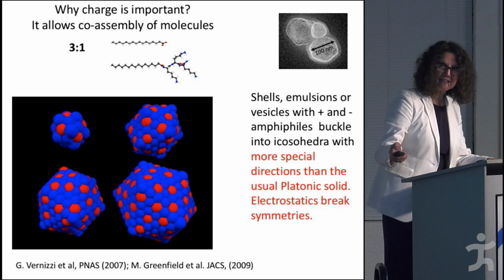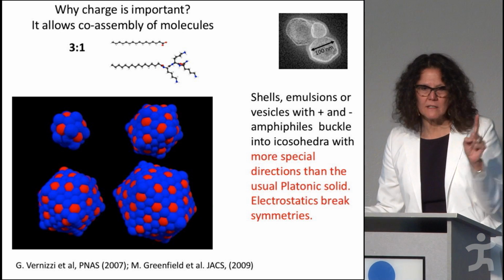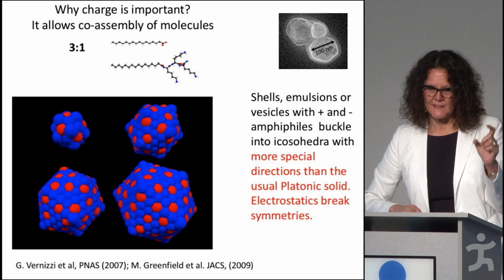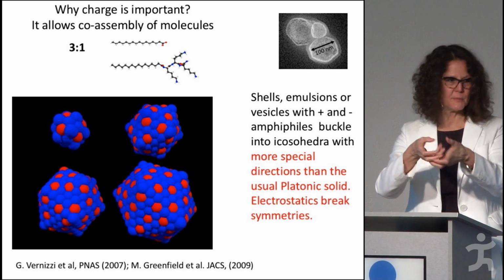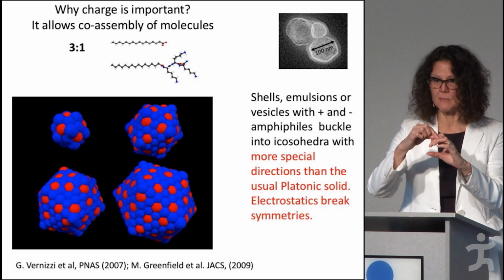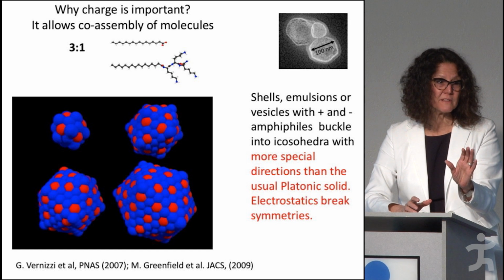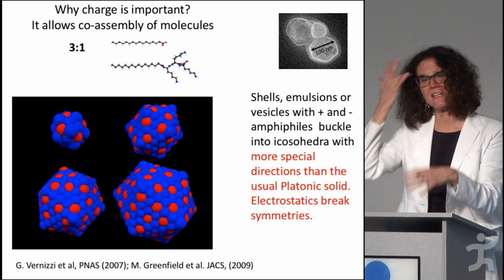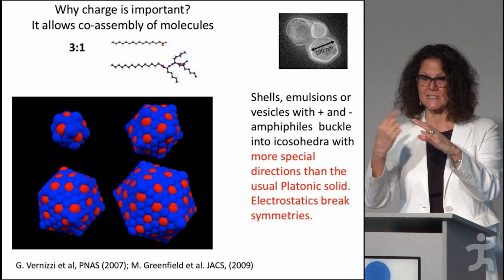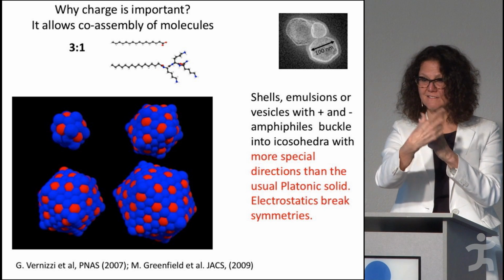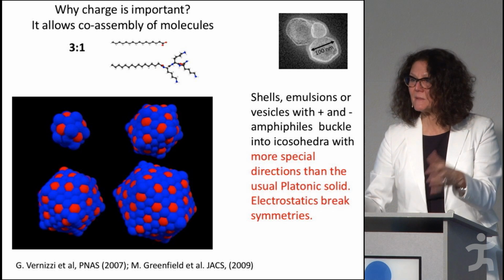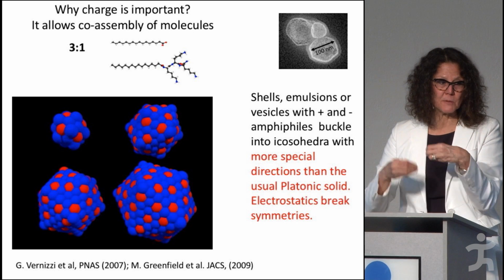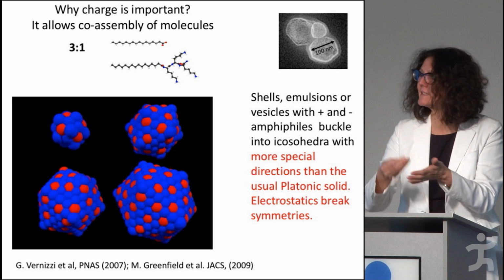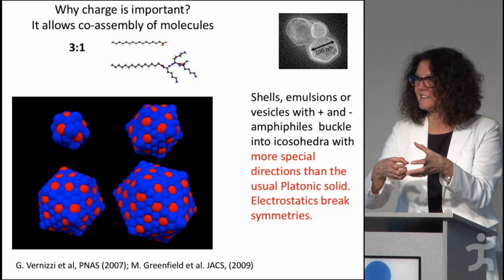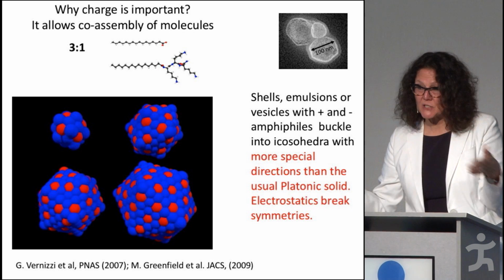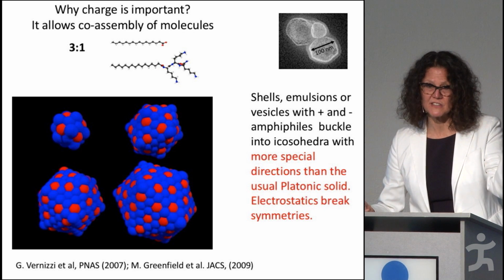And the resulting object, this was an icosahedron, but this icosahedron does not have icosahedral symmetry. And so let me explain this way. If you have a cube, it has a cube symmetry. But now if you are playing dice and you put labels 1, 2, 3, 4, 5, 6, now it doesn't have any more cube symmetry. You broke the symmetry because you have the labels. When these icosahedra have charges, what we find is that they break rotational symmetry, and each triangle in the icosahedra is not equivalent. They change the distribution. So it was very interesting because it means that this electrostatic interaction breaks symmetry spontaneously. And in order to have function, you have to break a symmetry. Okay? If you have something very symmetric, it's inert. So what I found very, very striking is that it's only this 1/r potential, which is the one we're made of, charges, 1/r Coulomb and so on.